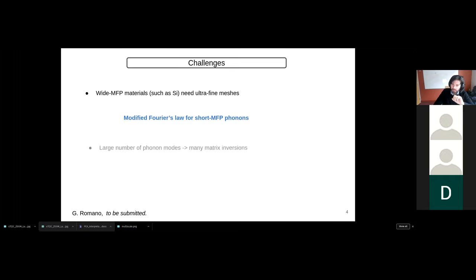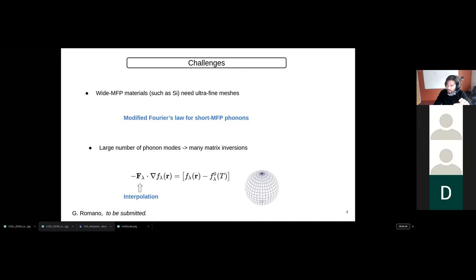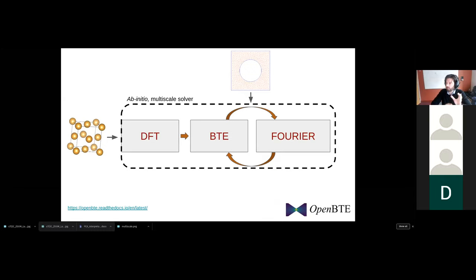Yet we still have to face another challenge. We have a large number of phonon modes coming from the DFT. It can easily be 100 or 1,000 modes, and we can't invert so many matrices. I mean, we can do it, but it can be a computational challenge. The way we do it is we reframe the RTA model by collectively describing the scattering time and the group velocity, translating those two factors into the vectorial mean free path. Here we can see that f lambda is a smooth function of the mean free path, so we can rely on interpolation. Instead of solving the BTE for thousands of modes, we solve it only for a set of modes that are uniformly distributed in a sphere, and then we compute the effective thermal conductivity simply by linear interpolation. This allowed us to simulate structures that go from the nanoscale all the way to the macro scales.